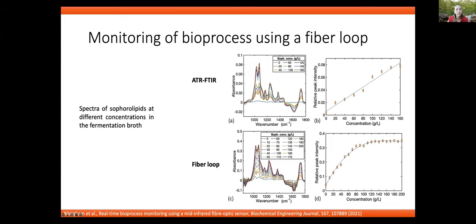One thing that this indicates is that over time, the sophorolipids just stick to the fiber, because with ATR-FTIR we cleaned the crystal in between, and here we actually put the fiber there and continuously measured. So there's some buildup of the different components onto the fiber end, which highlights the importance of developing different types of coatings or maybe cleaning rapidly and more often between the sampling, which is obviously not great for continuous monitoring. Those are the types of things that we are working on solving with our technologies.